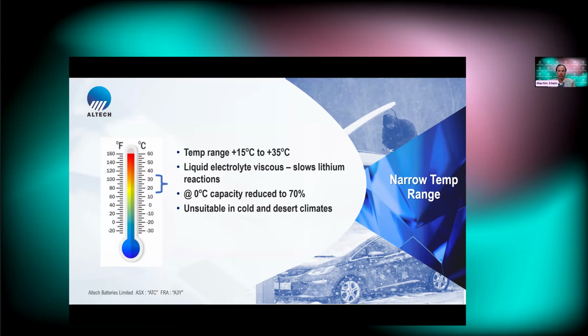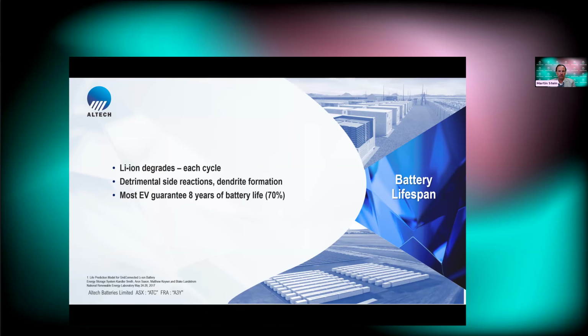They work very well between 15 degrees and 35 degrees, but if they fall outside of that temperature range, what happens is the electrolyte becomes viscous, and that reduces the efficiency of the charging and discharging. So lithium-ion batteries are not suitable for very cold or very hot desert climates. And they also have a limited life, just like your mobile phones. When they're first purchased, they have great charging and they last for a long time. But soon the lithium degrades. That's the same with grid storage batteries. And they're generally only operating for about 8 years.